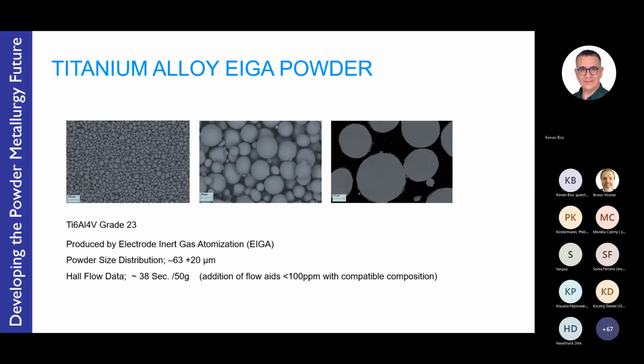Typically added as a nanoparticle, less than 100 ppm, with a compatible composition in many cases. So it's very hard to detect, but that guarantees good flow characteristics, and so far has no impact on final mechanical properties, although there's still more work to do in that area. Available with and without flow aids, I would say.